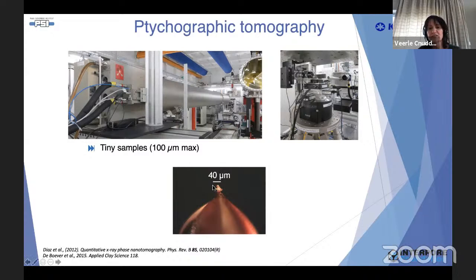A challenge was to produce a small sample, which is of course difficult when working with geological material. For that, we originally tried using a focused ion beam. Instead of milling material away for SEM images, we used the focused ion beam to mill material away in order to prepare a sample.